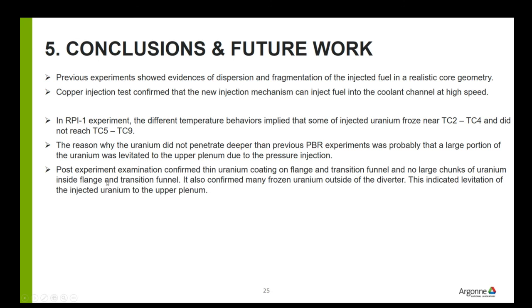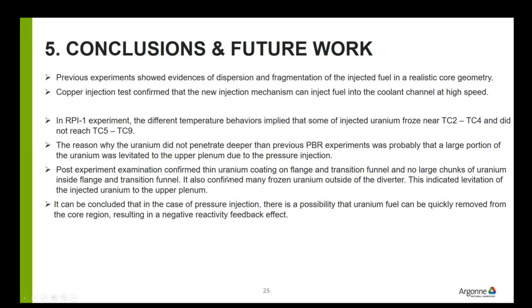Post-experiment examination confirmed a thin uranium coating on the flange and transition funnel, and no large chunks of uranium found inside the flange and transition funnel. It also confirmed that much frozen uranium was found outside of the diverter and transition funnel. This indicated the levitation of the injected uranium to the upper plenum. So we can conclude that in the case of pressure injection, there is a possibility that uranium can be quickly removed from the core region, which results in a negative reactivity feedback effect for the SFR, sodium-cooled fast reactor.